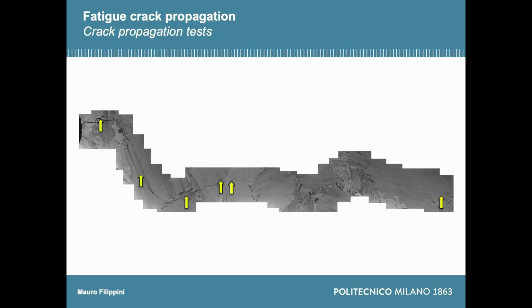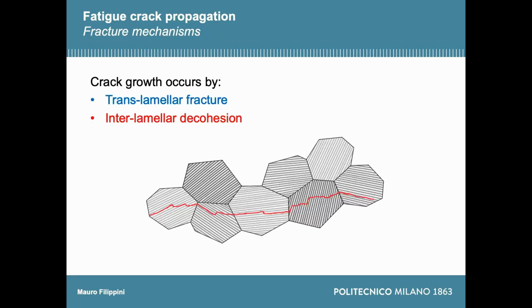Okay, so this is more or less the complete picture of this crack that has propagated through the microstructure. And you can observe that you already have some translamellar propagation. And when the crack is going through the lamella grains in this way, it is slowed down. Okay, so you might have a threshold due to the fact that the crack has a translamellar fracture.